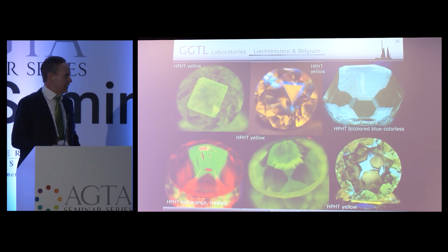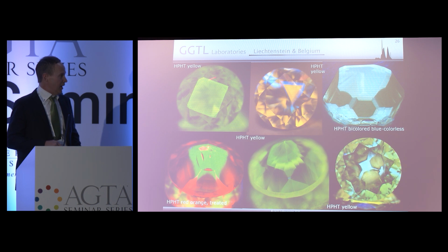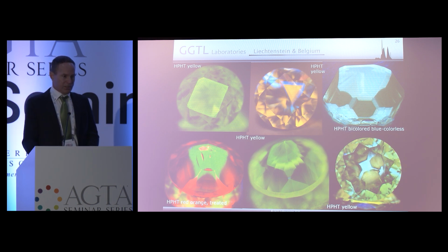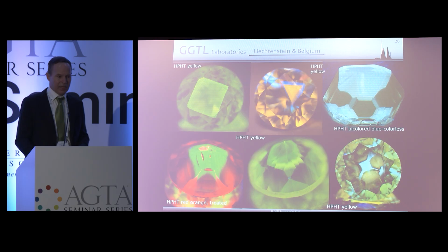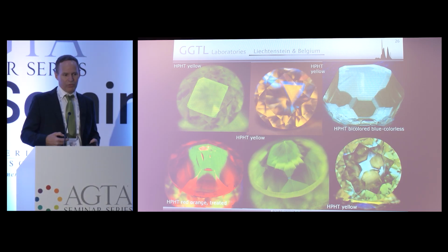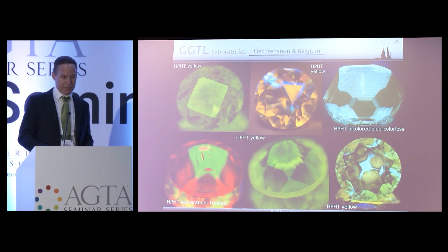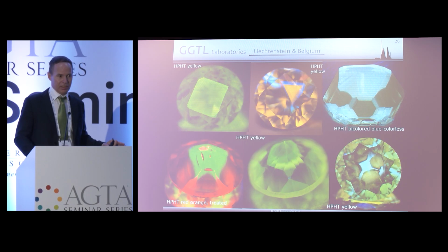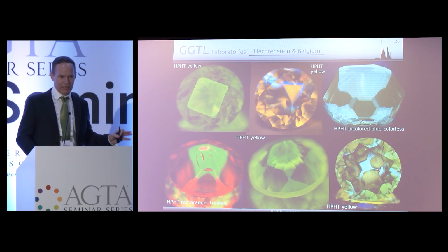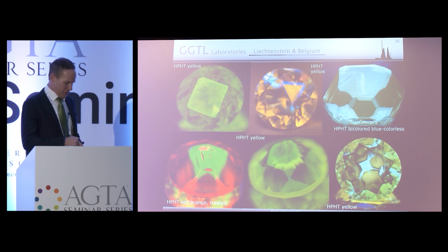It's one of the most challenging tasks of the lab to screen for HPHT synthetic yellows, especially when they're in really small sizes. When you get 10,000 stones and you need to know, are they natural, are they synthetic? It's really challenging because they have extremely variable properties that overlap quite a lot with natural stones, and they don't behave the same way. So it's not like HPHT synthetics in colorless, where you know deep UV, they fluoresce like that, and they phosphoresce. These things may fluoresce or not under any excitation, and they may phosphoresce or not under any excitation. And they may or may not show these features, so it's much, much more challenging to identify them.